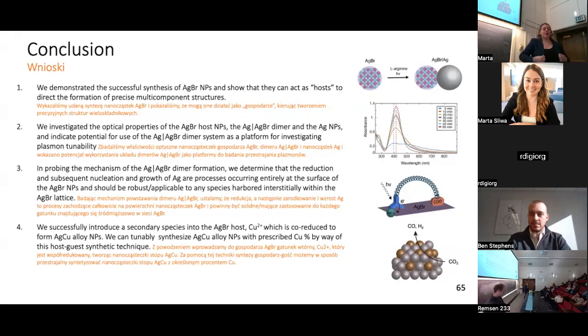So that is all thanks to that stabilizing oleate ligand that we introduced into the solution. At the solution pH, they form a nanoscale micelle that also very favorably interacts with the silver bromide surface, and in that way we quickly stabilize the nucleus of silver bromide within the solution with those oleate ligands when they're made. So we basically add the precursors to a highly concentrated solution of those oleate ligands.